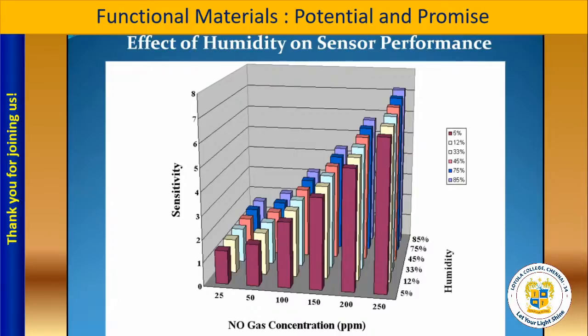Now, one thing which you worry about in the sensor world is humidity, because there is always humidity, and humidity kills sensors. No matter how wonderful the sensor, if you expose it to humid condition, humidity will kill the sensor response. Now you can see we have tested these sensors from 5% relative humidity to 85%. This is almost water, so you cannot have any more humidity than this. And in all conditions, the sensor is stable for a long period of time. This shows that at all the different relative humidities, the response and recovery time is perfect. So in a sense, this is a new breed of sensor materials.